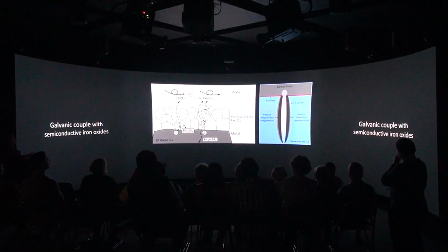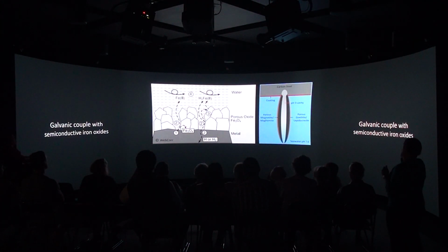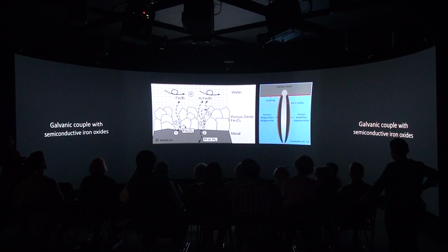And that's what's giving the rusticles the vertical growth that we saw in the last images. So this is my idea of a rusticle, and how it influences the corrosion process is precisely with this contact between the semiconductive iron oxides and the seawater at the tip. So this is just dissolved iron or iron chloride that leaches out, and once it reaches the oxygen, it precipitates. And then we'll see that they reach certain length or weight and they fall off.